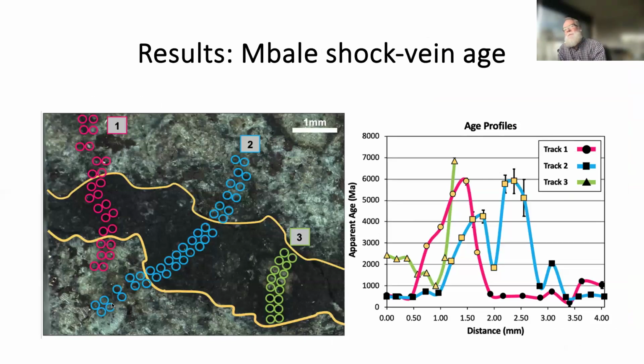My colleagues took a sample of this and put it in the UV laser microprobe, and this is what they got. They did 3 transects across a big melt vein. And what you see, so they're 1, 2, and 3. And let's focus on 1 first. Out here, before you hit the melt vein, they get an age of 500 million years. The age goes up to 6 billion years in the middle of the melt vein, and then back down to 500 million as we go out.